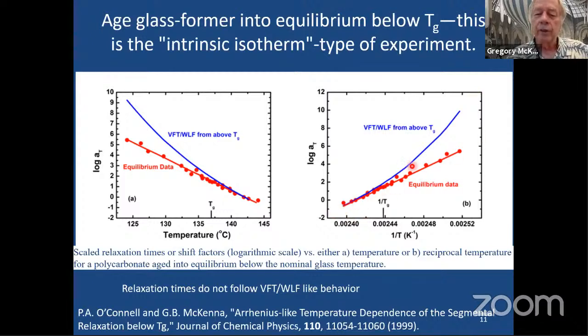It looks like, at least over this 15 or 20 degree temperature range, we have either an activated process, which would be the 1 over T, or it's almost a straight line also in log shift factor versus temperature. That would mean it was an exponential in temperature rather than in reciprocal temperature, which might mean it's still different from the Arrhenius type of idea, but the activation energy.